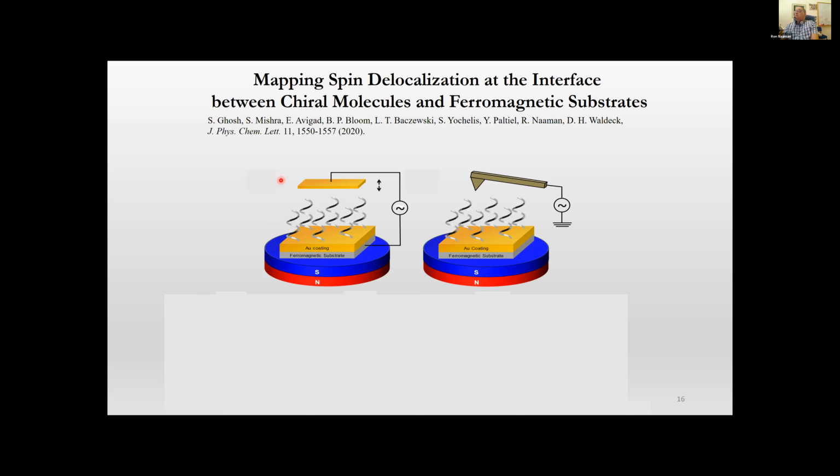And because the electrochemical potential on the surface is different than the electrochemical potential on the substrate, we get current flowing when we vibrate. We can, of course, then zero the current by applying voltage. This way, we learn about the different voltage, or the different work function, if you wish, of the substrate and the reference in the Kelvin probe. We use two types of Kelvin probes, either a macroscopic one or one that is based on atomic force microscopy.